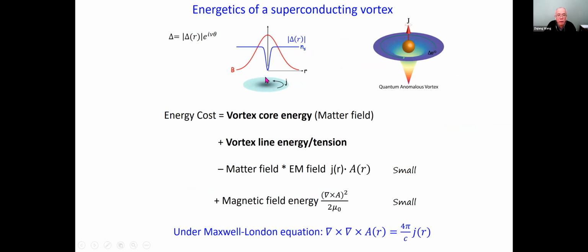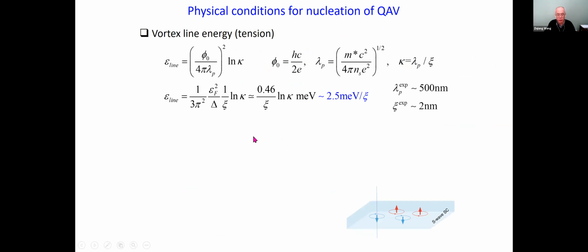Now, a few words about the energy cost of the vortices. Basically, the main parts are two contributions. The core energy, which is really the penalty you pay for creating a vortex. And also there is a vortex line tension, which is the line energy. And you can estimate this for FeTeSe. Here this is just BCS estimates, but you have experimental parameters. The main point I want to point out is the line tension is a function of E_F squared over delta. So being in the extreme quantum limit for FeTeSe tells you that the number you can get is 2.5 meV per coherence length. So the line tension is very small. So the vortices are very floppy. They're easy to bend, to manipulate. And if you did the same thing for cuprates, you get something on the order of 800 meV.